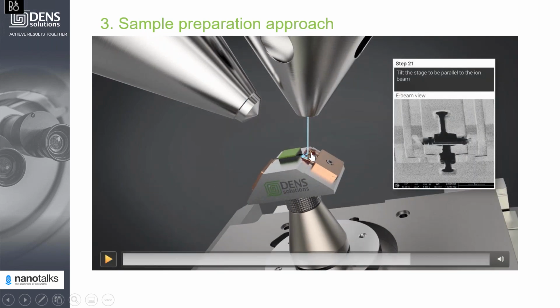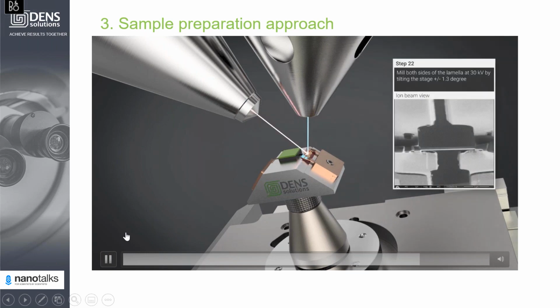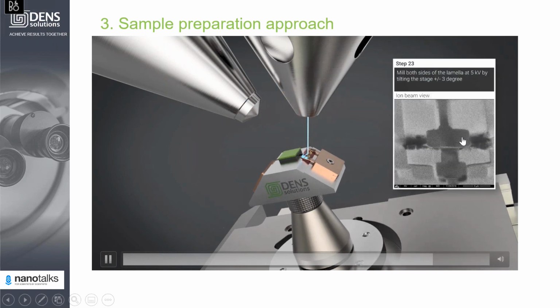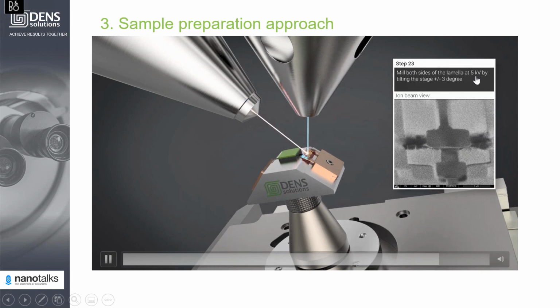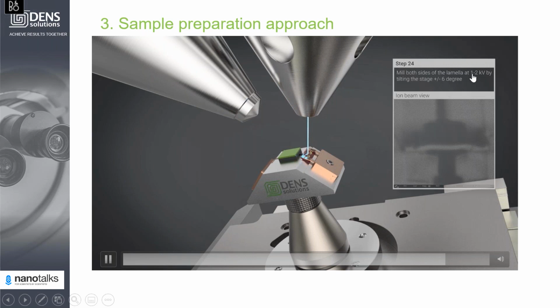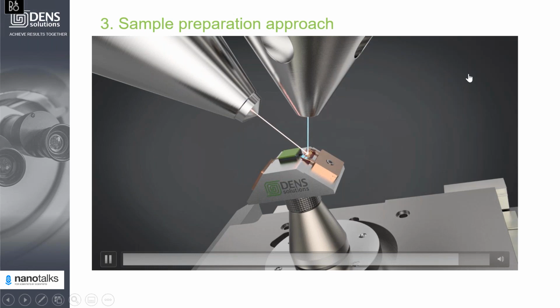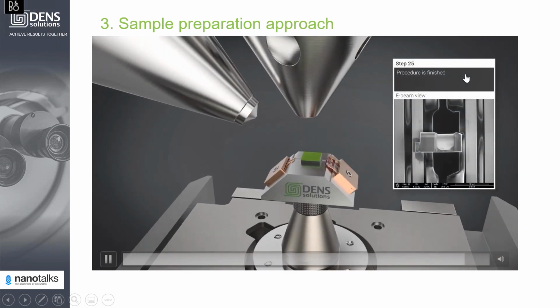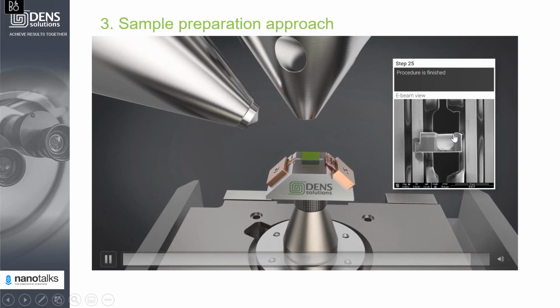Then during the next step, you tilt the Nano-Chip, well, not lamella, sorry, Nano-Chip, to have the lamella parallel to the ion beam. And the next process, actually, you can use the same process you're using with Omni grids. So what you do, at 30 kV you use relatively high currents and small tilts to mill it down to 100 to 200 nanometers. Then you reduce the accelerating voltage to 5 kV. And then as a final step, use 1 to 2 kV at a larger angle to polish the sample to remove the amorphous layer. And when you have the desired thickness and the quality, you basically stop the process.